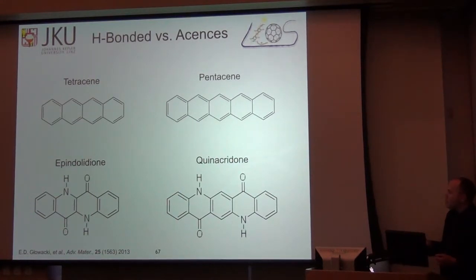And here we compare two hydrogen-bonded pigments, epindolidone, which is a yellow inkjet toner in Epson printers, and quinacridone, which is a magenta inkjet printer pigment, but it's also pink hair dye that's produced in extremely large commercial quantities. This is a 5-member ring, kind of analogous to pentacene, and this is a 4-member ring, kind of analogous to tetracene, but the presence of these amine keto groups completely blocks the intramolecular conjugation as described before. So now our conjugation is basically limited to one benzene ring along these molecules.